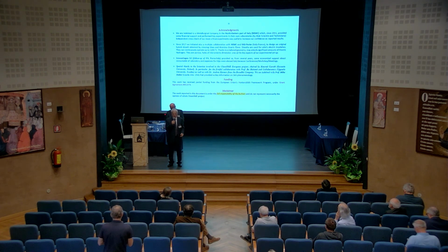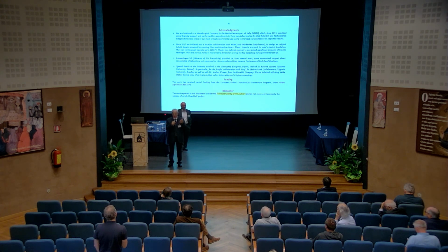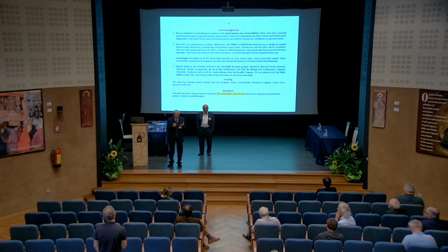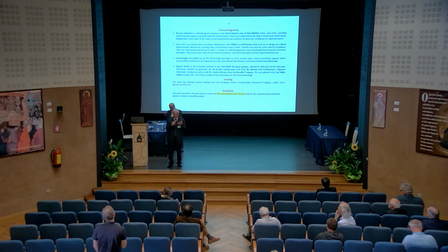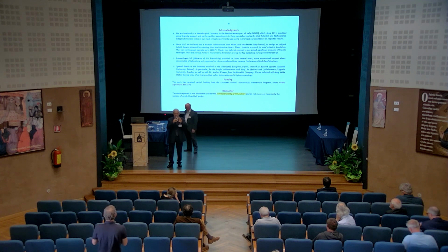Okay, we've done several experiments using pulse conditions. The pulse enhances the effect for several reasons. One is local concentration. One is local extra heat. So there are several effects altogether. But it's complicated. So people say, oh, we cannot understand, and we move back to DC. So this is the point. But we found that just leaving it for a long time, 1 week, 2 weeks, we have a similar effect to pulse, but at a lower intensity. So the origin is the same.